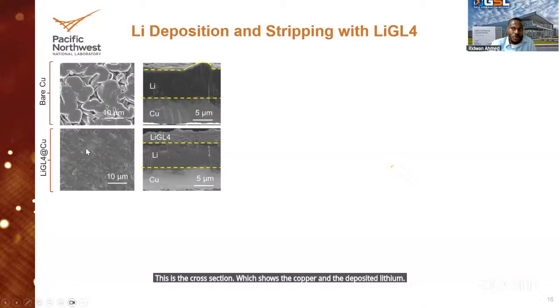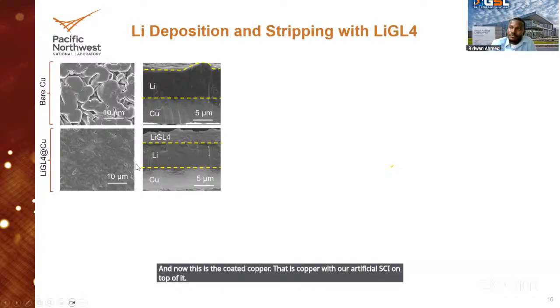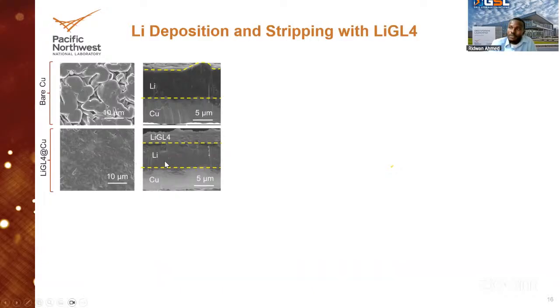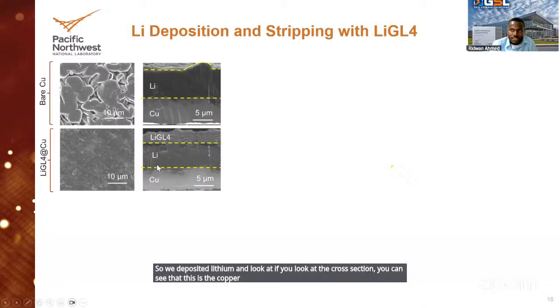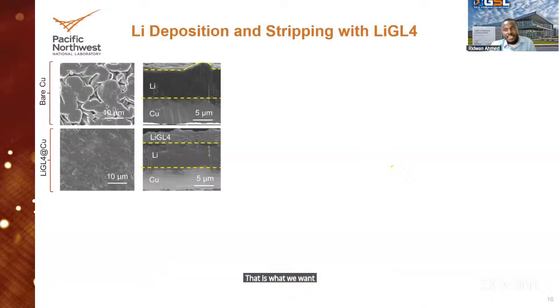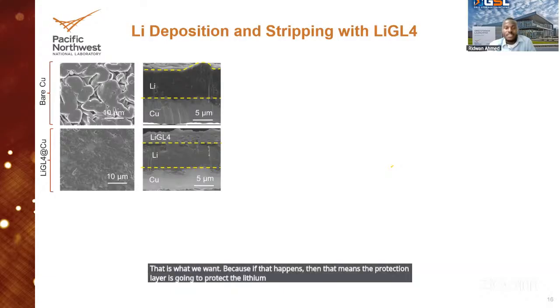And now this is the coated copper. That is copper with our artificial SEI on top of it. So we deposited lithium, and if you look at the cross section, you can see that this is the copper, this is the deposited lithium, and this is the coating layer. Which means the lithium is deposited beneath the coating layer. That is what we want. Because if that happens, then the protection layer is going to protect the lithium from reacting with the electrolyte.